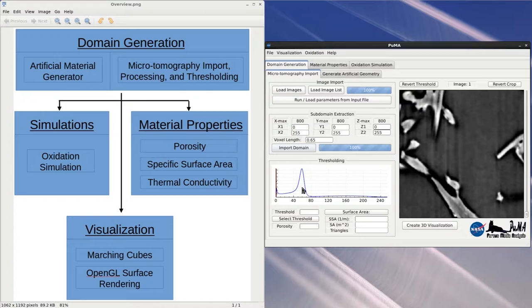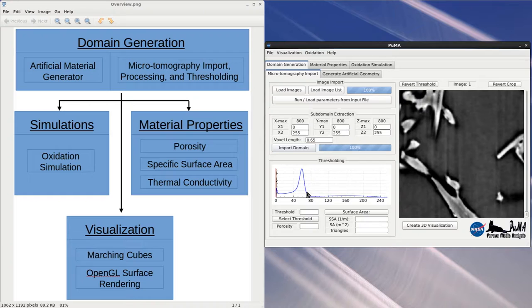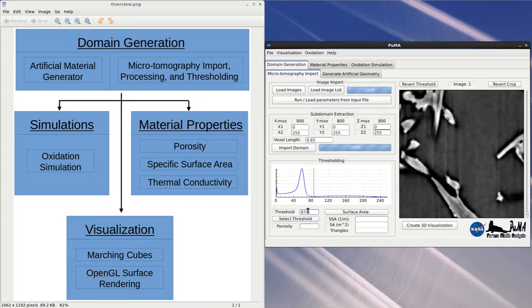There are two peaks on the plot. The first, larger peak, is the average grayscale value of the voids. The second peak is the average grayscale value of the material. We have to select a value between these two peaks approximately at the inflection point at which anything above or at this value will be considered material and anything below will be considered void. For the provided sample of fiber form, a value of 87 was found to be appropriate as a threshold value.